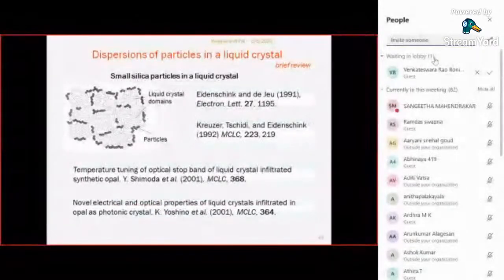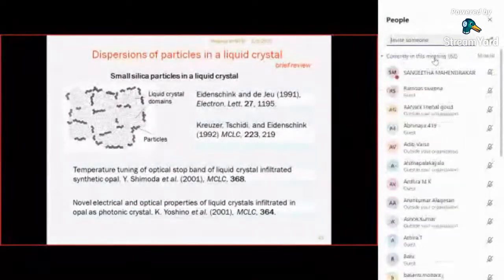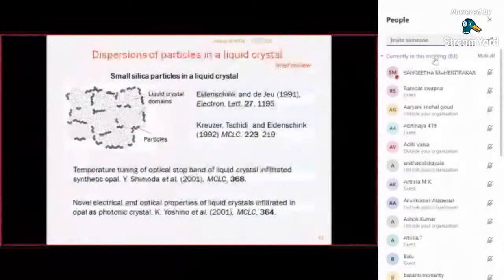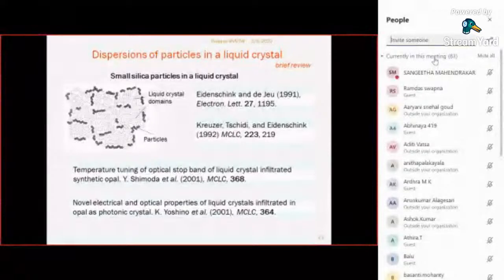So this is the result which I am going to show. Silica nanoparticle. I have also worked on silica nanoparticle in liquid crystal, but I am taking the example from this paper. These are liquid crystal domains, and when you embed or dope nanoparticles into liquid crystal, nanoparticles have a segregation problem. So how can it be solved? We want the particle not to segregate into the liquid crystal matrix.